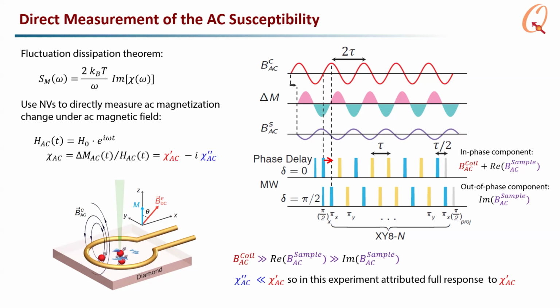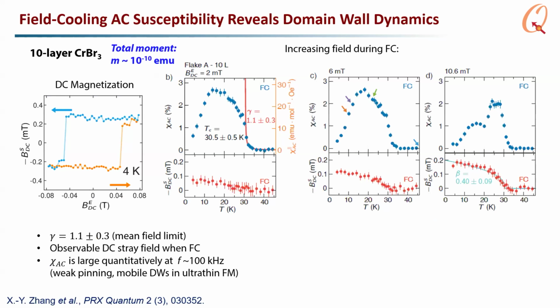So in this first experiment, we only measured the real part of the AC response. We basically attributed all of the AC signal amplitude that we got to the real part. Then we can measure how much the coil produces by going above TC or going away from the flake. So here's a 2D ferromagnet, chromium bromide. We can measure the AC susceptibility in a 10-layer thick chromium bromide. That was limited not by our NV sensitivity, but by our exfoliation techniques at the time. This is actually the first paper out of my group, but it's still pretty good.